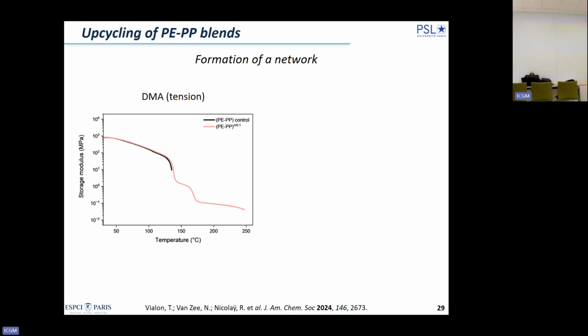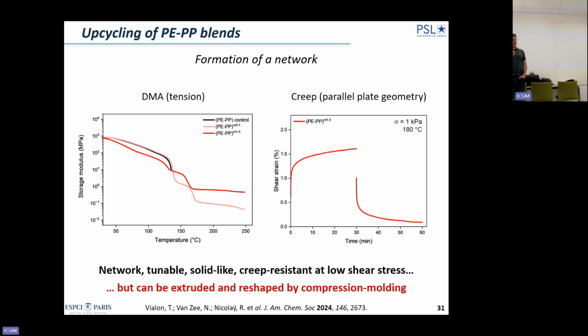Now, when it is crosslinked with 0.1 mole%, we have the melting of PE here, we have the melting of PP here, and we can still measure an elastic modulus, pretty low. And if we increase the amount to 1 mole%, we can now see a rubbery plateau. So we were able to crosslink the material. It is not fully crosslinked, but there is a chemical network in it. And if we do the same creep experiment at 180 degrees Celsius, this material is also creep resistant. So this is something which is really unusual.